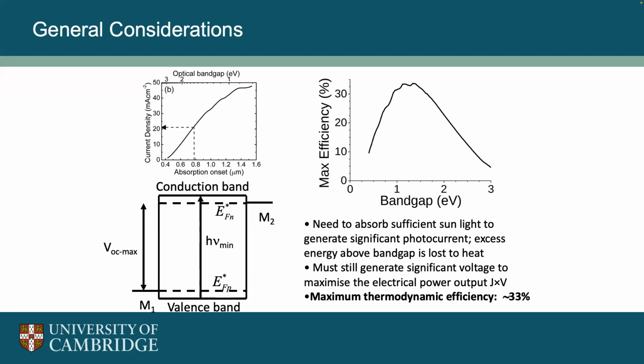So yeah, we certainly are thinking about these things. There are some issues. With silicon panels, in fact, there is lead in the solder, and that can be an issue that can leach out, although it's quite well contained in the encapsulation. The perovskites do have lead in them. It's very small amounts when you think about these extremely thin films, but we are thinking particularly about encapsulation methods to package them well and make sure that even if there's catastrophic failure, there won't be any leakage. And it also raises the interesting question about recycling the panels at the end as well.